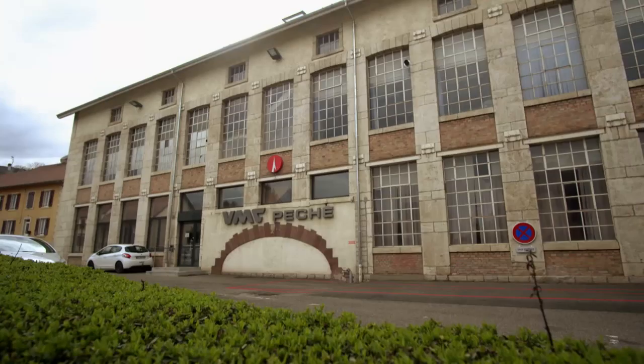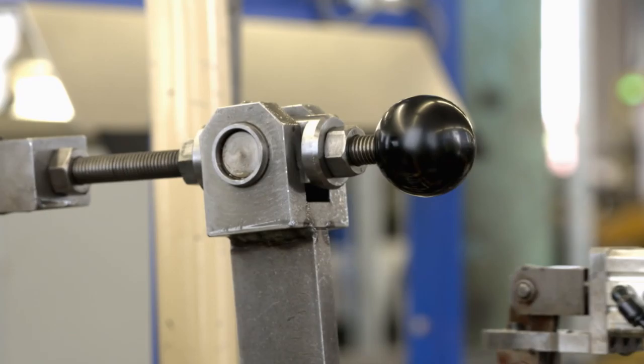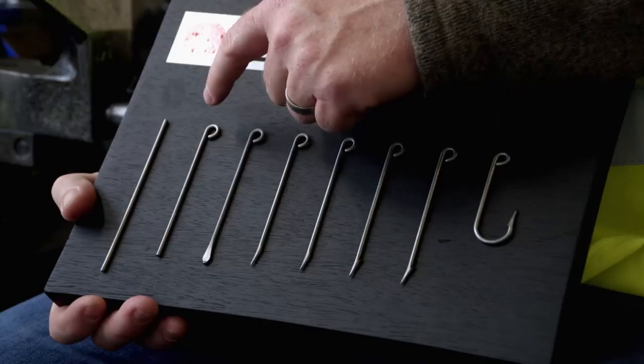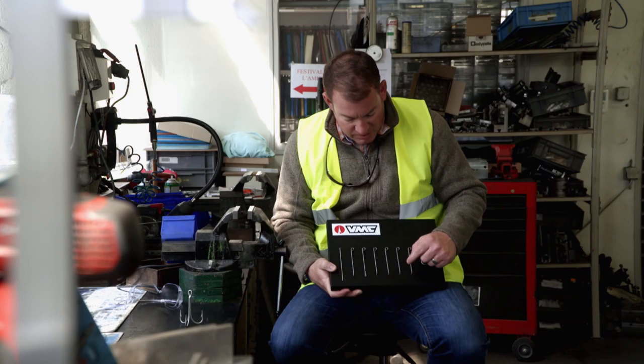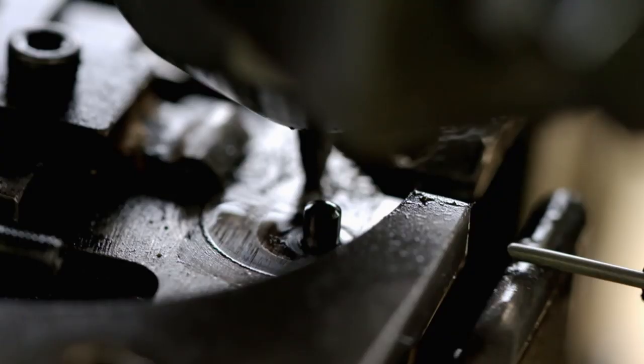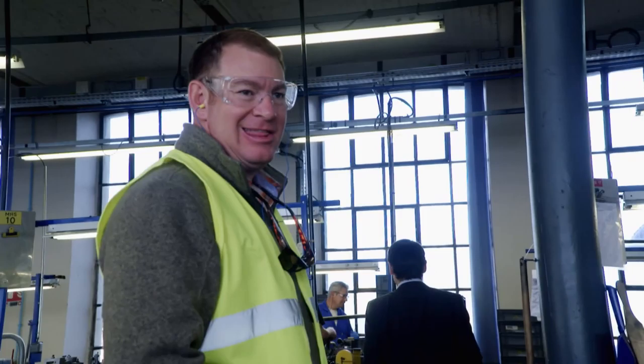In the faraway French village of Morvillars, VMC's machines eternally twist and turn out fishing hooks. VMC is a little bit secretive about their technology, but here are the eight steps: first the machine cuts and straightens the wire, then they add the eye, forge the end to flatten it, cut it to size, do a coarse grind to sharpen it, add the barb, do a razor-sharp finish on the tip, and then they shape the hook. They have a bunch of these machines doing the same thing — that's how they get to six million hooks a day.